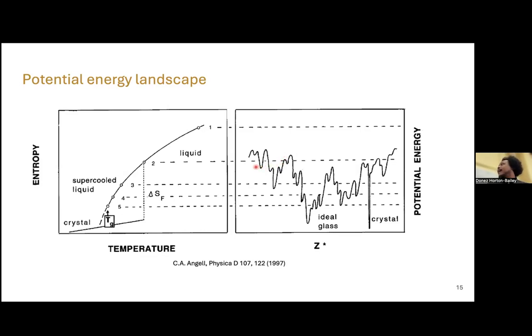But the main thing is that at the bottom of each of these wells is a quantum state, as I mentioned before. So each of these states at the bottom of each well represents a different configuration of atoms. So in a crystal, every atom has a correct position, and there's one crystal structure, or there might be several, but there's one crystal structure, and you have one state way down here where there are no other states nearby. That's the state that you're in. But for all of these other states, these are all glass states. These are all amorphous states. And you have some states that are nearby each other. They're very close to each other, and you can actually change states by having atoms move around in your material.